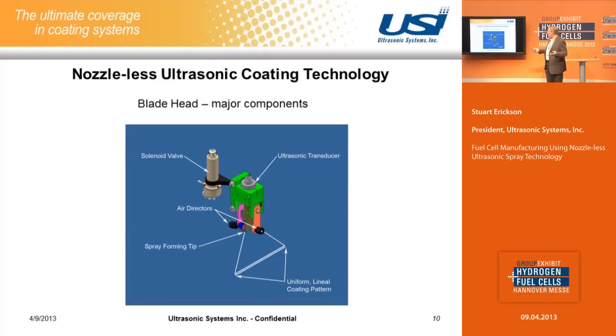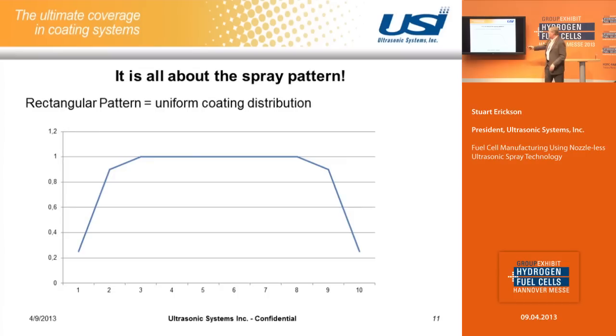And then our ultrasonic spray head, and I'll go into this in more detail, makes a rectangular coating pattern. A rectangular coating pattern means that the coating pattern is more even across the width of the pattern, and then it feathers off on the edges. So you get a much more uniform spray pattern with a single pass with the ultrasonic nozzle-free technology.